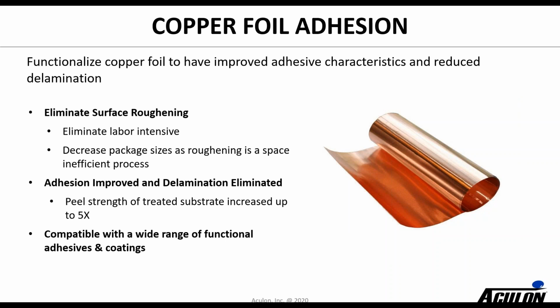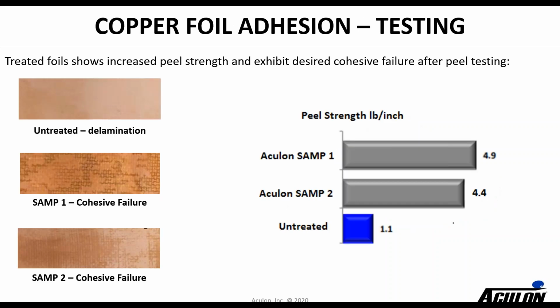Another space that's been really important in the electronics area is copper foil. We've been able to really help do a couple things. One is there's been a strong desire, as the electronics have gone to higher and higher frequencies, to reduce some of the roughness that was typically used to get mechanical interlock of resins into copper. With our technology, you can remove a lot of that roughening, and so that has some good advantages. And then we've been able, in a lot of cases, to increase the strength up to 5x, which is great, and really help improve adhesion between copper foil and resins.